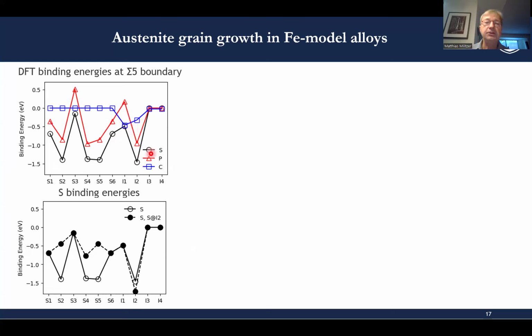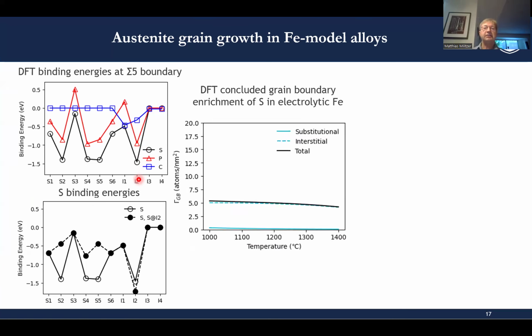And when we look a little bit closer at what happens with sulfur, when sulfur occupies an interstitial site, it essentially eliminates segregation to the substitutional sites or reduces the binding energy to these sites quite significantly. And so it's really the competition of carbon and sulfur and to some degree phosphorus for the interstitial segregation position. So if you do the analysis now for this electrolytic iron with whatever, 31 ppm sulfur, what we found is that at the temperatures of interest this interstitial site is usually occupied, and we get a grain boundary enrichment of sulfur that is predicted to be 5 atoms per square nanometer. And then we can do the analysis for describing the grain growth behavior.